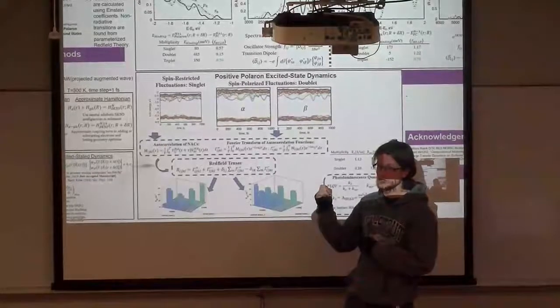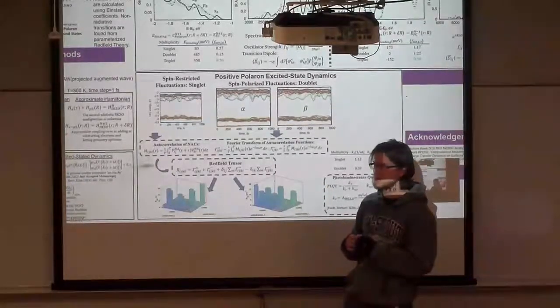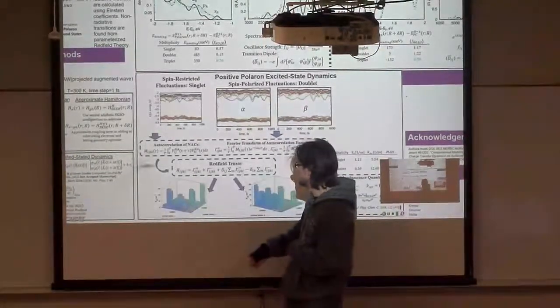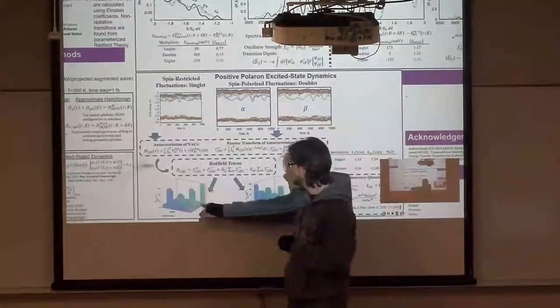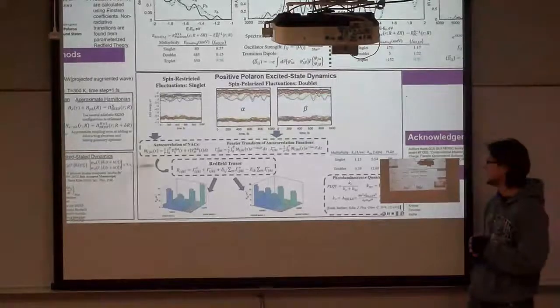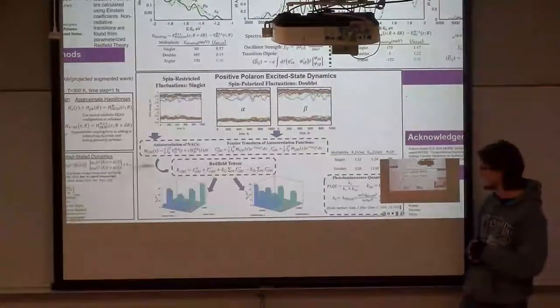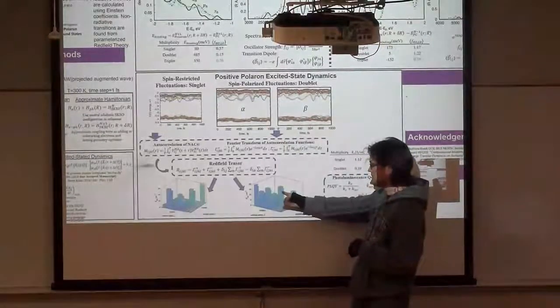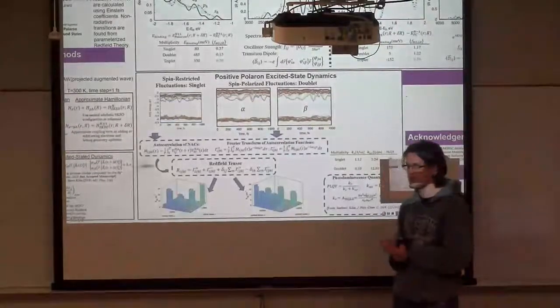Upward transitions are weighted by a factor of e^(-ΔE/kT), so they're pretty much negligible. So we're basically just looking at these two terms. And those are visualized as our Redfield tensors at the bottom here, which represent state-to-state transitions between orbitals. Our X and Y axes are orbitals, and then the Z components describe rates of transitions between the orbitals.